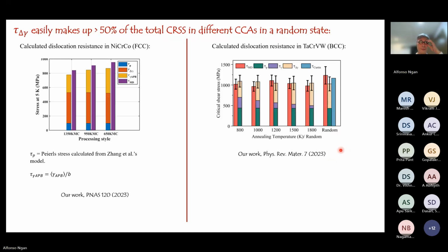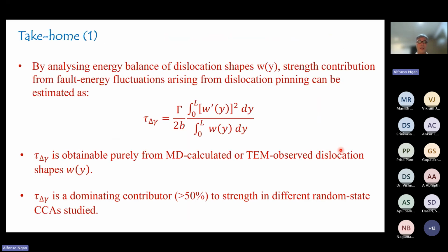So take home number one: by analyzing the energy balance of dislocation shapes, we can calculate the strengthening factor due to the fluctuating atomic environment, represented by the fluctuating gamma, the fault energy. This doesn't involve any strong assumptions because it can be obtained from purely MD simulation or TEM observed dislocation shapes. And this term is a dominating factor, easily more than half of the strength.